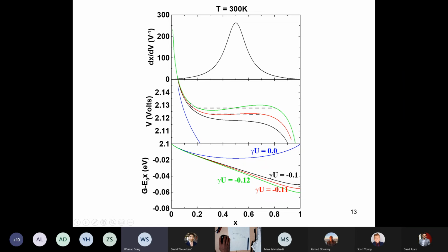It will follow this point and come to the black dash curve and follow the black dash line and then back to the green line again. So this explains why when we see these flat lines, it normally means there is phase separation occurring in the electrochemical reaction. Okay, thank you. Correct. Yeah. So like LFP is doing this all the time. Okay, thank you, Jeff.